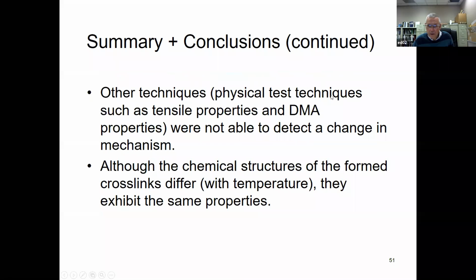Other physical testing techniques, such as tensile properties and DMA properties, were not able to detect a change in mechanism. Although the chemical structures of the formed crosslinks differ with temperature, they exhibit the same properties. So it's actually a very nice conclusion. You can do your accelerated oven aging and measure the properties, and understand that those properties are the same as if they were aged for a longer time at lower temperature.